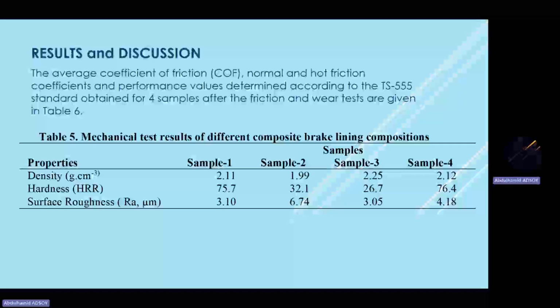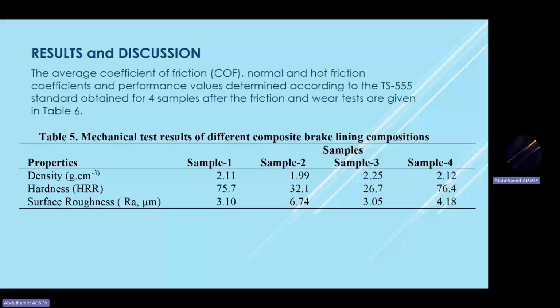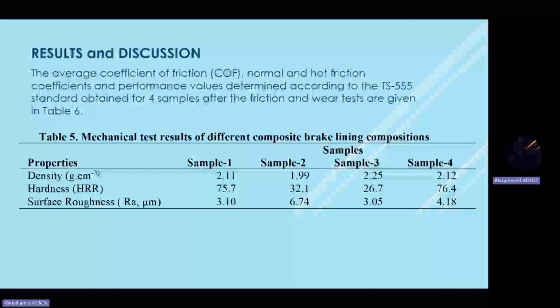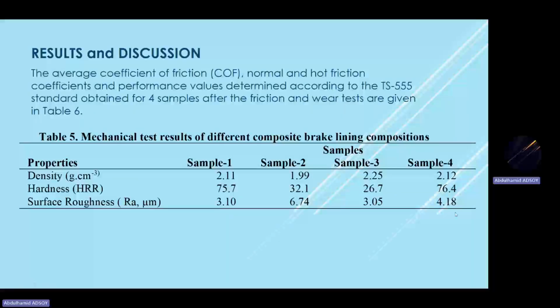Now, apart from this, one of the important parameters in brake pads are density and hardness. The density and hardness of the materials were also measured, and also the worn surface analysis was done by a roughness measurement. And as we can see, the samples that contain rubber have a higher surface roughness than the ones that don't contain rubber, meaning the rubber increases the surface roughness. And because of the rubber particles, also the porosity of the samples increases with the use of tire rubber.